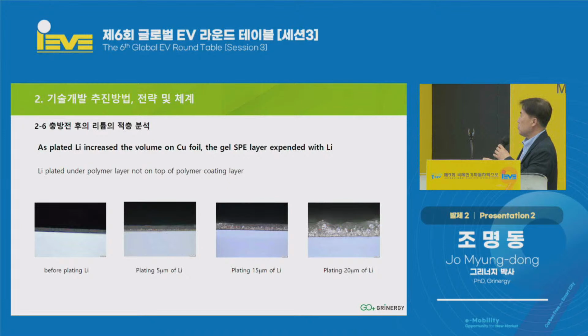And we've done, once again, a before and after plating. You can see the 15 micron plating, the dendrite, as it grows, the gel polymer is not torn, but rather it's well covered. And if we plate with 20 micron, you can see right here that the dendrites are growing so much. And even though it is penetrating the gel polymer, still the gel polymer is well covering the dendrites. So we are very encouraged. Even though it's 20 micron, still the gel polymer is well covering dendrite. It's well preserving dendrites. So we can tell that the testing results were really great.